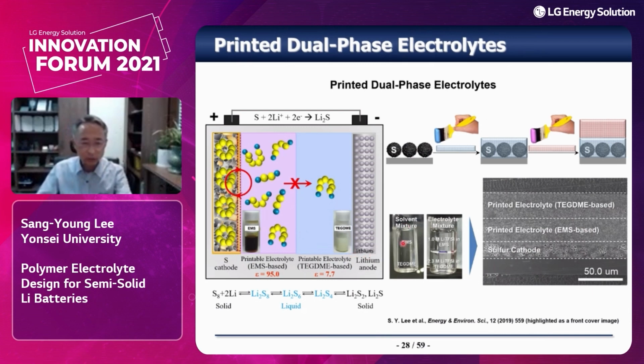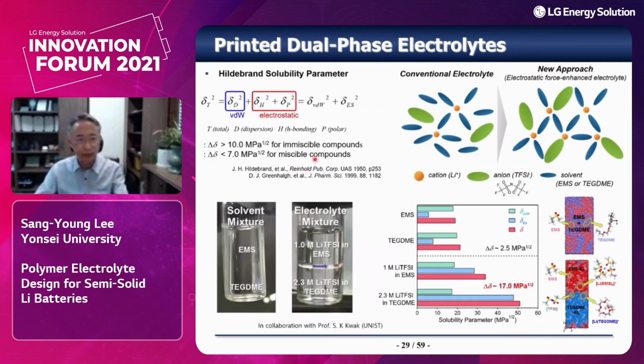The interesting point is that the solvents themselves are miscible together. However, when we control the salt concentration, we can separate the two electrolytes like this, which is based on coordinated electrolyte chemistry. Using this electrolyte, we have introduced different types of printed electrolyte like this. So here are more details on how to design the dual phase electrolyte based on the coordinated electrolyte chemistry.